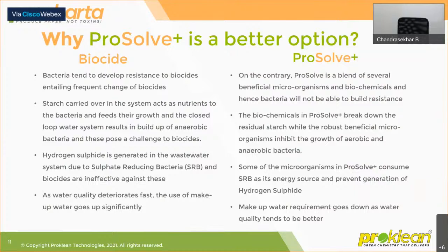So they keep on developing. Whereas the biochemicals in ProSolve+ not only break down the starch, but the beneficial microbes start utilizing it and grow and build a strong defense. Thirdly, biocides are not known to be very effective against sulfate-reducing bacteria, which is why packaging mills create so much odor. Whereas with our microbes, there are some of them which consume SRB as their energy source, which is why the hydrogen sulfide generation is significantly reduced.